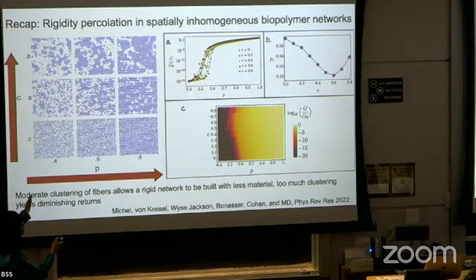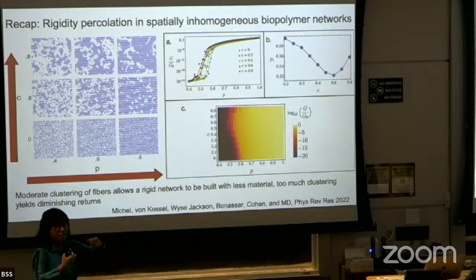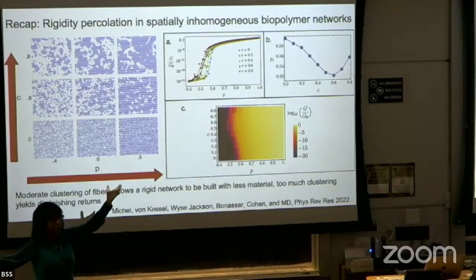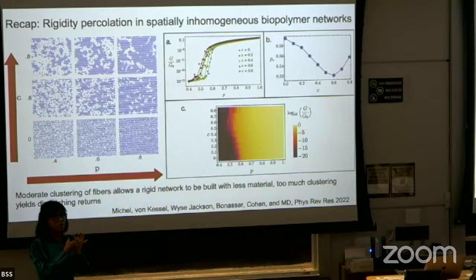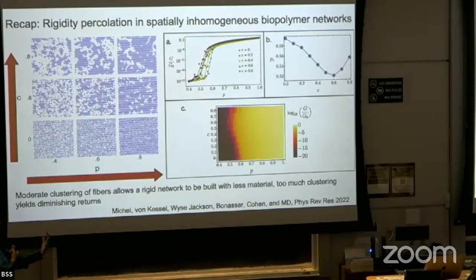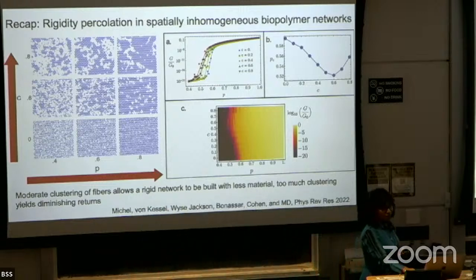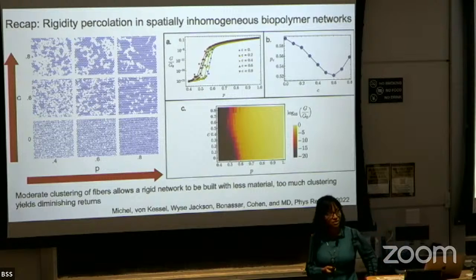And what I showed you is that initially, as things are more and more clustered, my percolation threshold keeps moving to smaller and smaller values of P, but then it will not be monotonic. At a point, it will start coming back, right? So this is what we see. And that's because initially, as you have more and more connected regions, you can have a path of force transmission over long distances with fewer filaments. However, if you have too much correlation, you can have completely disconnected islands, right? Where you can't have that. So a moderate amount of correlation is good, but like everything in life, too much correlation is probably not good. So everything in moderation, right? So there is sort of an optimum window. All right, so this is where we had left off in last class. Yes, question.